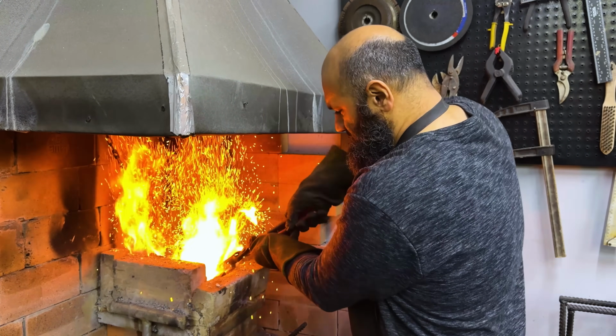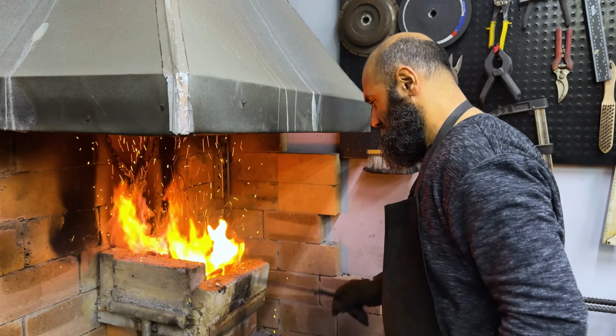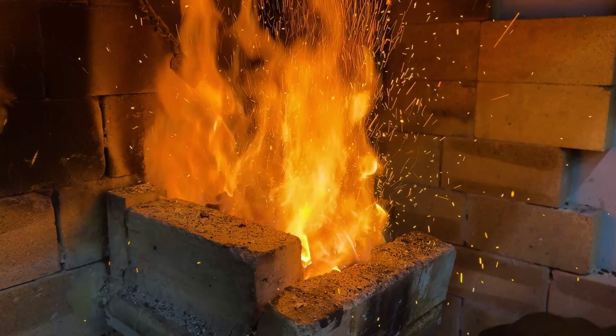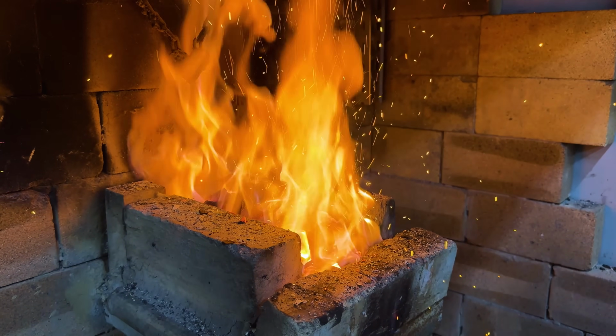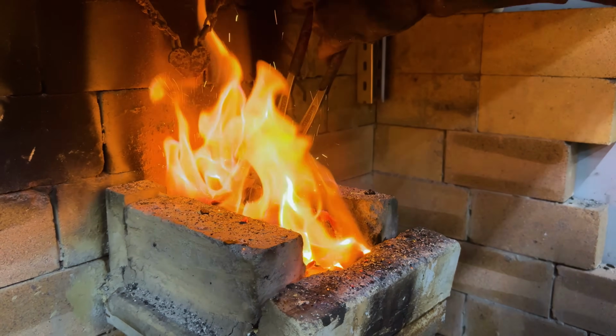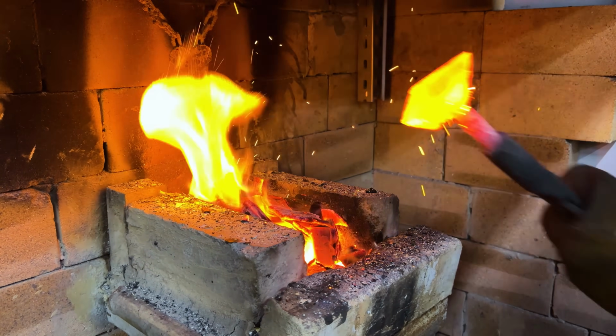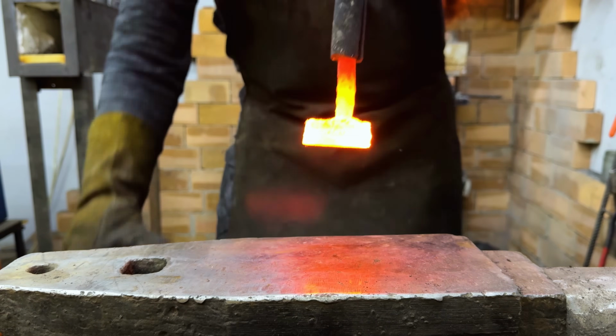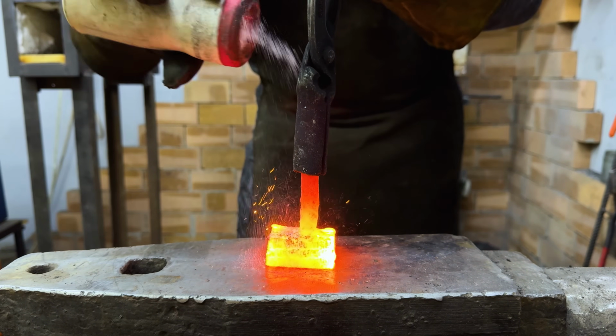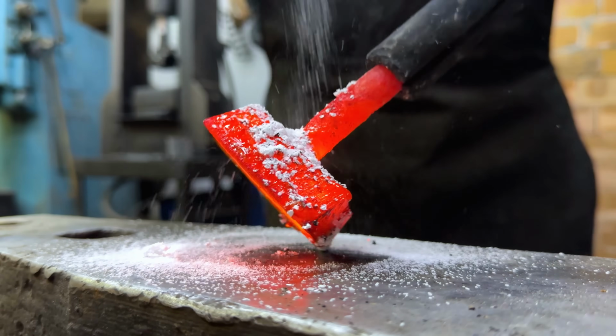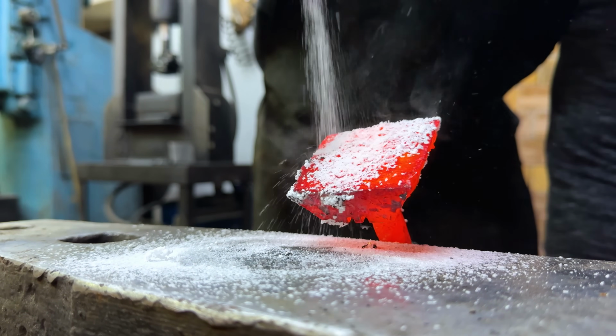Now for the magic dust. This is welding flux, typically a compound of borax or a commercial anhydrous mixture. When it hits the hot steel, it melts, dissolving any iron oxide, scale, and acting as a barrier to prevent more oxygen from reaching the layers. It creates an airtight liquid shield, and without this, the weld fails.